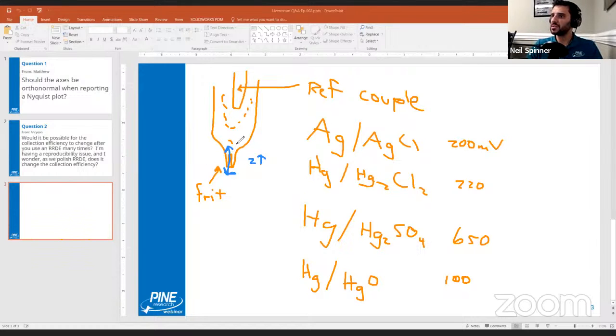The other is that because there's some diffusion in and out here, well, if you have silver chloride or calomel, for example, the supporting electrolyte in here is usually something like KCl or NaCl. So this means that you have chloride ions inside here. Well, that means that necessarily, slowly, but still over some period of time, you might have chloride making its way into the main solution. Chloride is often undesirable, especially if you're doing very, very sensitive electrochemistry. If you're not so concerned about it, it doesn't necessarily affect your experiment.